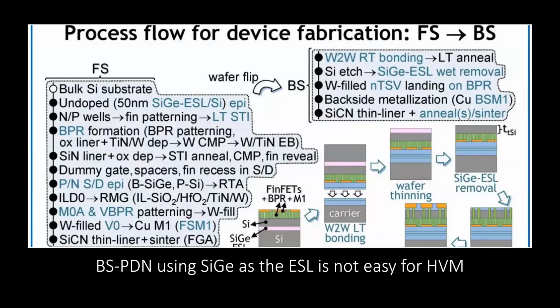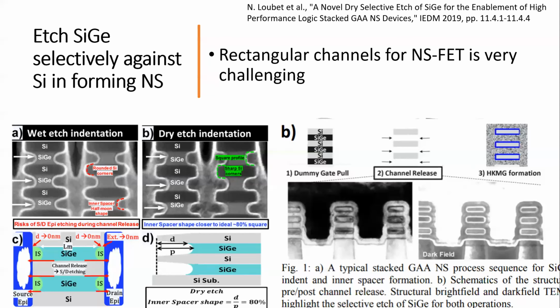Okay. So now let's look at, since we're going to talk about using SiGe as the stop layer, why I say here is not ready for high volume manufacturing. What do I mean by that? All right. Let's go one step at a time. Before we go into SiGe, at the end of the day, we're going to etch it. So we're talking about etch selectivity against silicon in forming the nanosheet. And there are two versions of it. One is to etch SiGe and not etch silicon, or etch silicon and not etch SiGe.